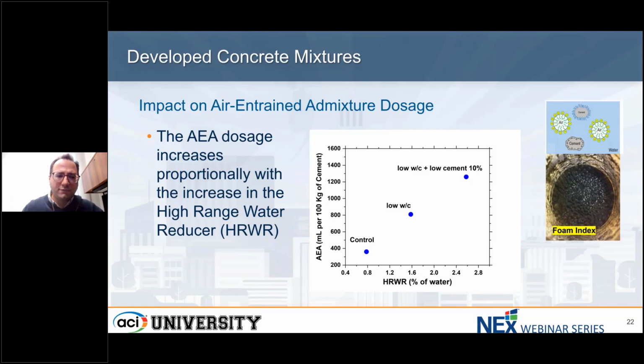The other important fresh property is the air content. As we know, when we are using a high dose of water reducing admixture with the air entraining admixture, that can impact the quality of our air content. It can reduce air content and kind of destabilize the air admixture. So we wanted to see how this new system we are developing impacts that air content requirement. To do that, we used the foam index test shown at the right side. We tested different concentrations of high range water reducer, and we measured what air entraining admixture content is required to have a stable foam index, right?